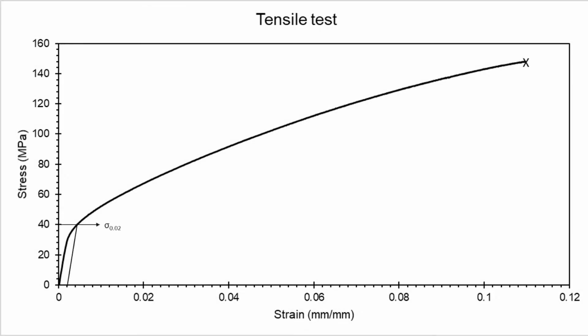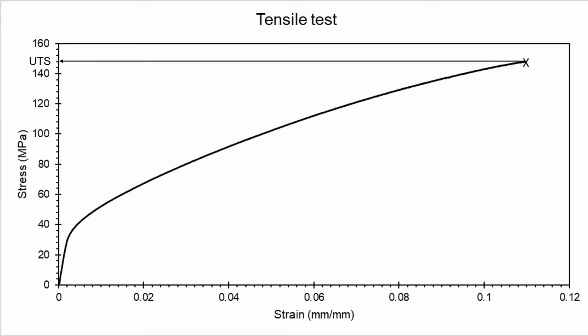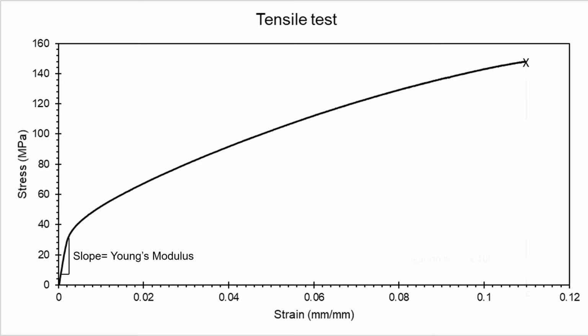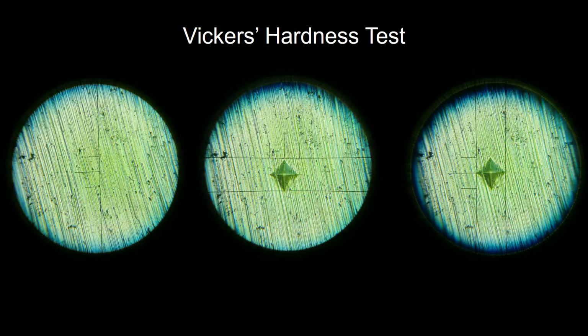In order to determine the mechanical properties of the alloys, we perform tensile tests, from which we obtain the alloy's yield strength, ultimate tensile strength, elongation percent, and Young's modulus. We also perform rigorous hardness tests, in which an indentation on the surface of the material is made and measured. This allows us to quantify the resistance of a material to plastic deformation.